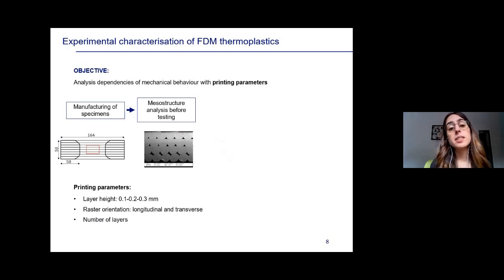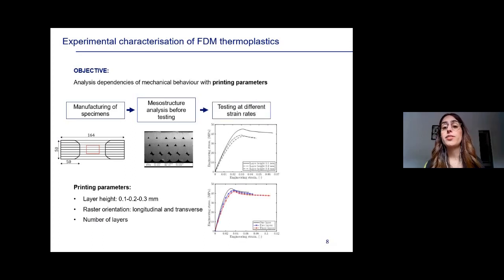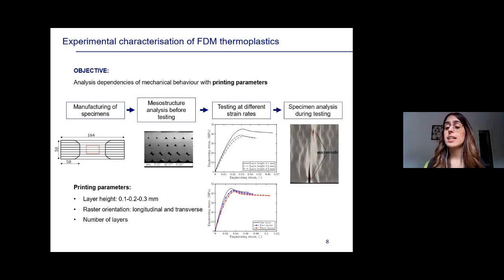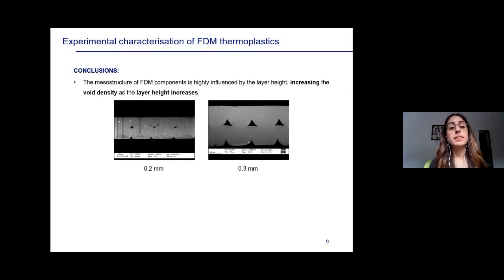Once we manufactured the specimens, we analyzed the mesostructure of these new materials under a scanning electron microscope. Then we carried out different tensile tests at different strain rates, and finally we analyzed the failure of these materials during and after testing. Analyzing the mesostructure, we observed that the mesostructure of fused deposition modeling components is highly influenced by the layer height, and we observed that the void density increased as the layer height increased.